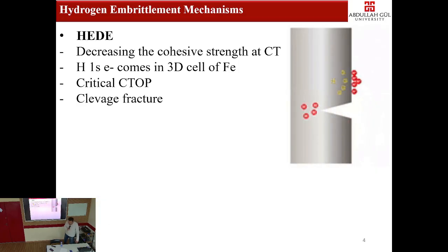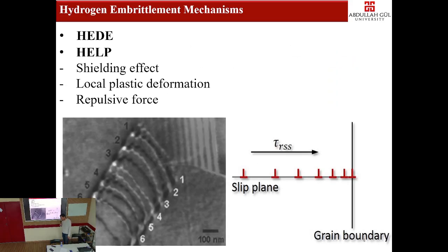There are several mechanisms proposed to explain hydrogen embrittlement. I tried to summarize some of them. Hydrogen enhanced decohesion is one of them. It states that hydrogen, while it's moving, decreases the cohesive energy of the bonding, and this causes brittle failure. Hydrogen enhanced localized decohesion. The second mechanism is hydrogen enhanced localized plasticity.